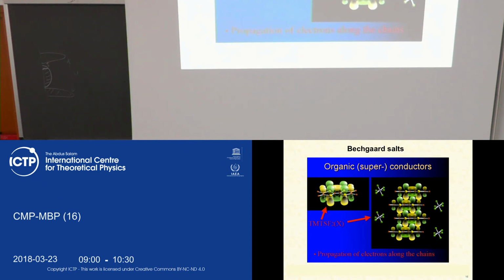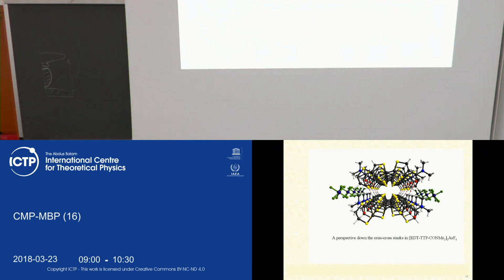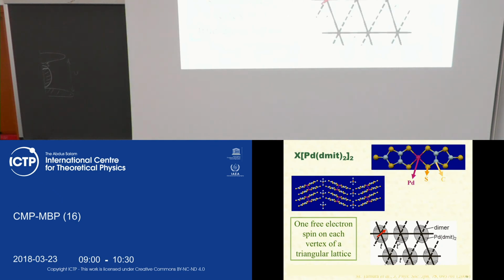For example, both Little and Ginzburg suggested the so-called exciton mechanism of superconductivity. Because, again, going to lower and lower dimensions increases fluctuations, increases correlations, and as we see, competing interactions can lead to high temperatures of superconductivity. So this is how these quasi-one-dimensional systems look like, and here we arrive at many interesting playgrounds for quasi-one-dimensional systems.